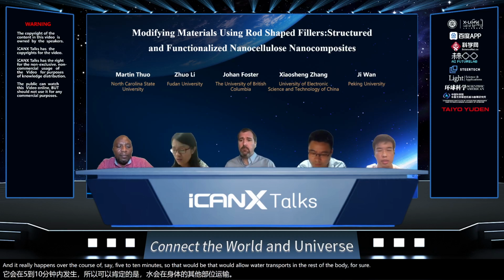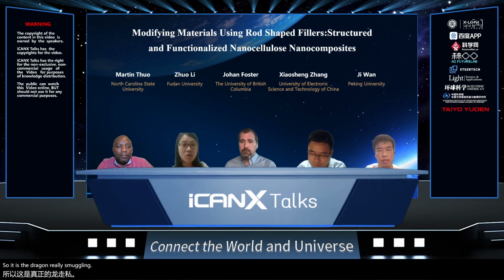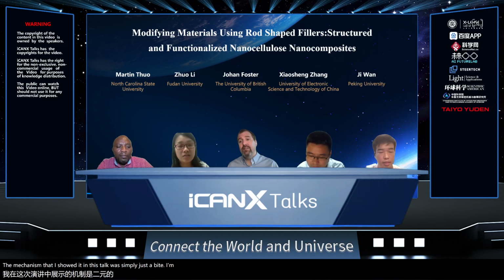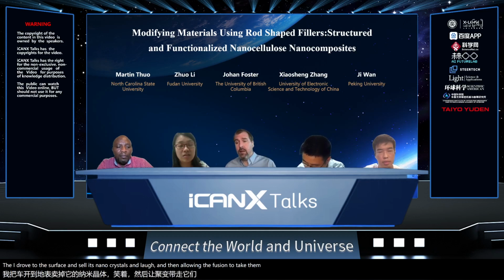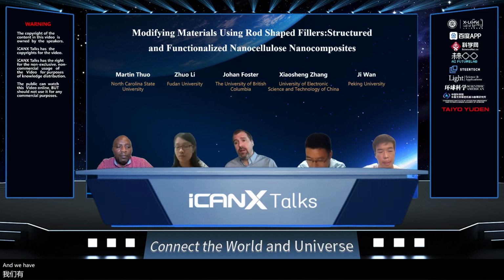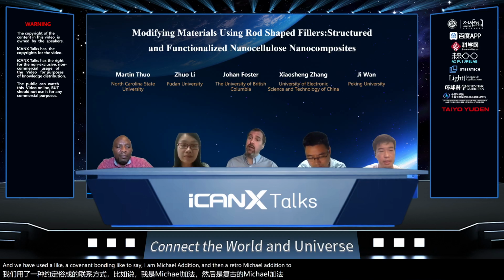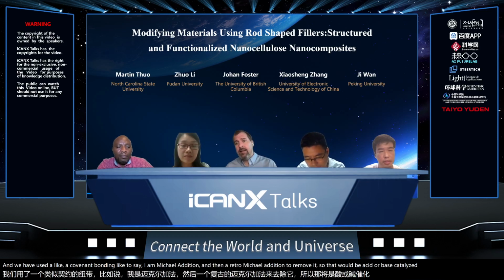I see. So is the drug release mechanism more or less related to the hydrogen bonding between the CNC as well? Yes, the mechanism that I showed in this talk was simply just adhering the drugs to the surface of the cellulose nanocrystals, and then allowing diffusion to take them out of the composite. We have used covalent bonding, like say a Michael addition and then a retro Michael addition to remove it. So that would be acid or base catalyzed. But in this case, no, it was just simply adhesion to the surface.